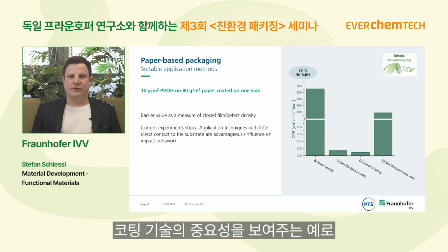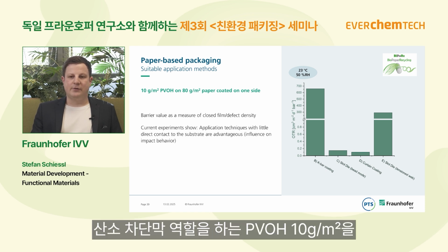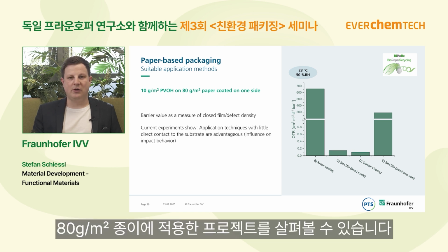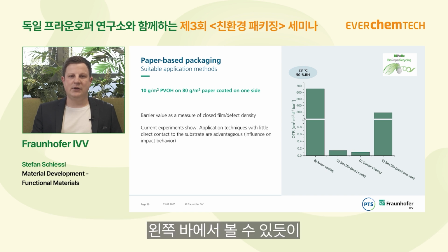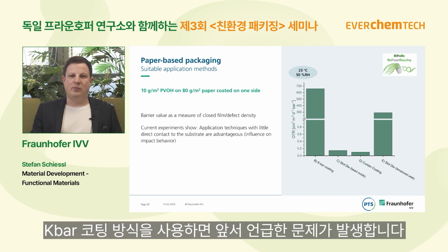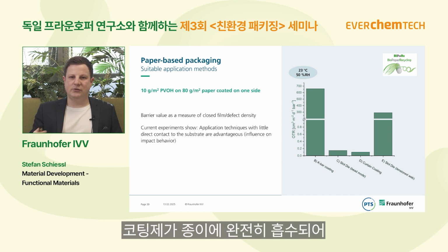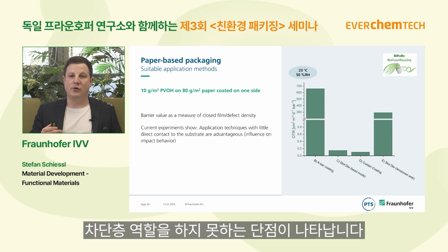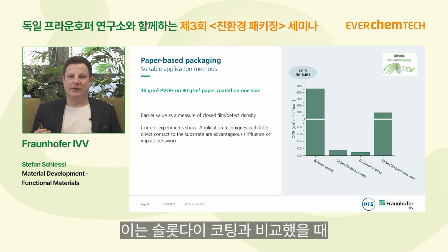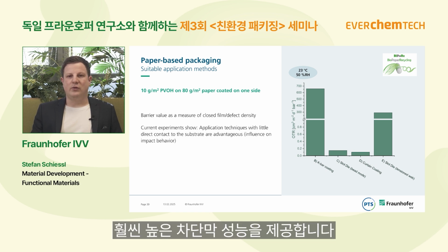The importance of the coating technique on paper is shown on this example from a project where we coated 10 grams per square meter PVOH, which is a typical barrier lacquer for oxygen, on an 80 gram paper. And as you can see on the left bar, when we apply the lacquer by K-bar, then it is exactly happening what I talked about before. The complete lacquer is pressed into the paper and we have kind of an immersed paper but not a coated paper, and this leads to a very high barrier value